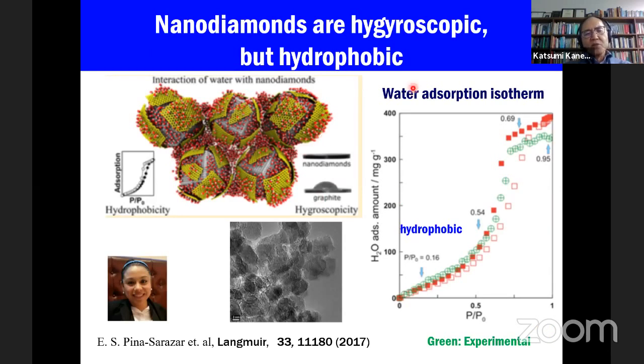And very recently, we observed very unique behavior on nanodiamonds. Here I will show you a TEM image, not so large, but inside we can observe the real cubic form of the nanodiamonds, but the outermost surface is coated with a graphene-like structure. Between the graphene-like structure and the core nanodiamonds, which are around 3 to 4 nanometers, there are ultramicropores, and water is adsorbed at ambient conditions.